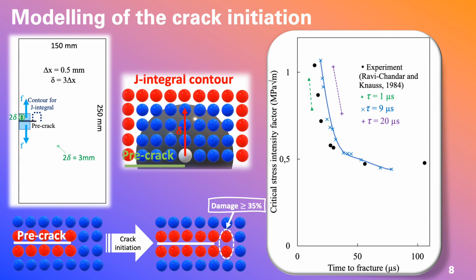As a result, dependence of the stress intensity factor on time to fracture was obtained, and it adequately predicts the experimental dependence when tau is equal to 9 microseconds. Additionally, results for the different values of tau were obtained. Also, we can find transition of obtained dependence to the quasi-static critical stress intensity value that demonstrates independence of incubation time criterion on significance of the inertial effects, that is a crucial feature of this approach.